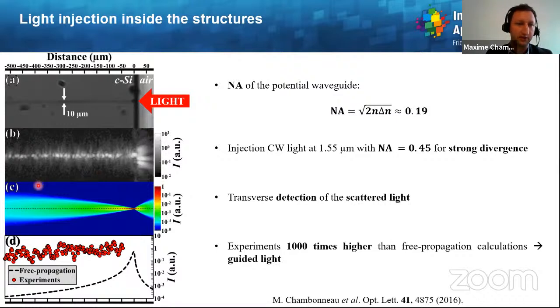And besides, we have carried out here in C and D an evaluation of the linear propagation in silicon, if one assumes that there is no guidance. So first, we can evaluate the numerical aperture of the potential waveguide, which is around 0.2. And the injection of the light with a high numerical aperture objective will allow us to have a strong divergence. So it's easier for us when we use a numerical aperture which is much higher than the one of the potential waveguide. It is much more convenient to see if light has been guided.